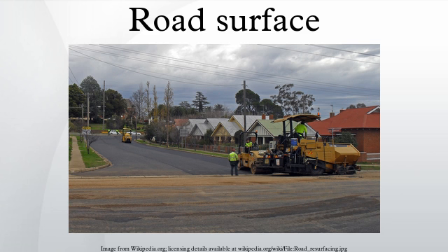Depending on the temperature at which it is applied, asphalt is categorized as hot mix, warm mix, or cold mix. Hot mix asphalt is applied at temperatures over 300°F with a free-floating screed. Warm mix asphalt is applied at temperatures of 200°-250°F, resulting in reduced energy usage and emissions of volatile organic compounds. Cold mix asphalt is often used on lower volume rural roads, where hot mix asphalt would cool too much on the long trip from the asphalt plant to the construction site.